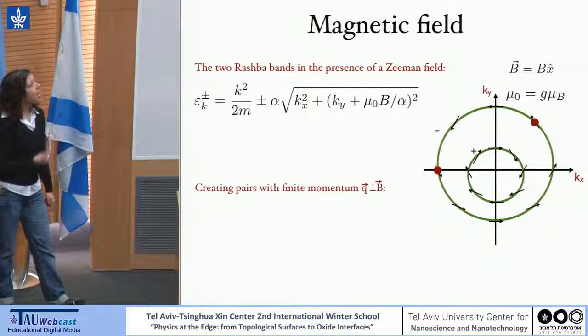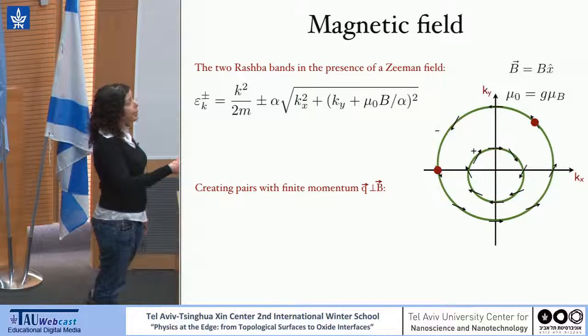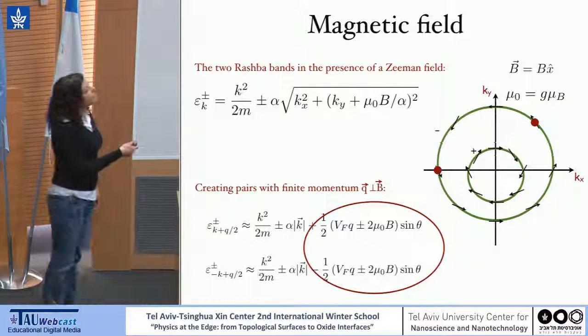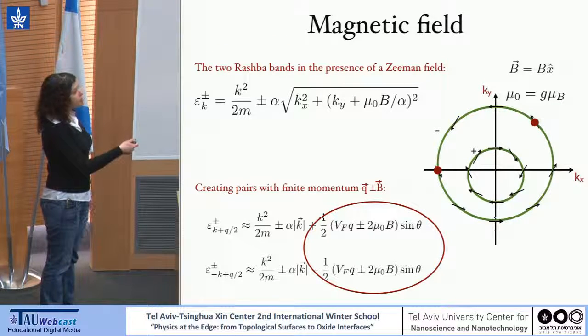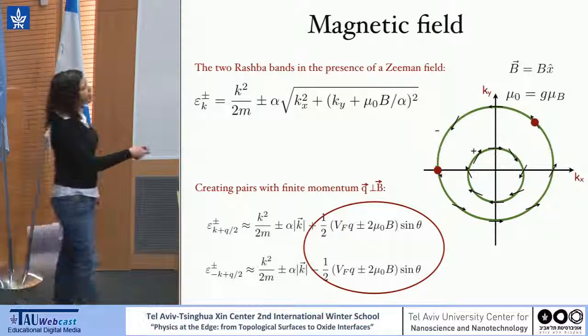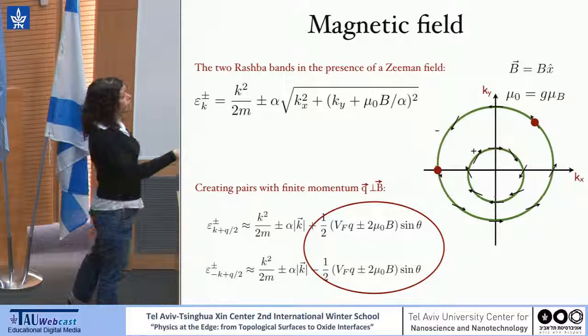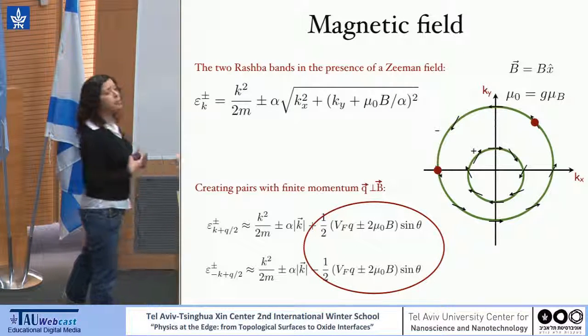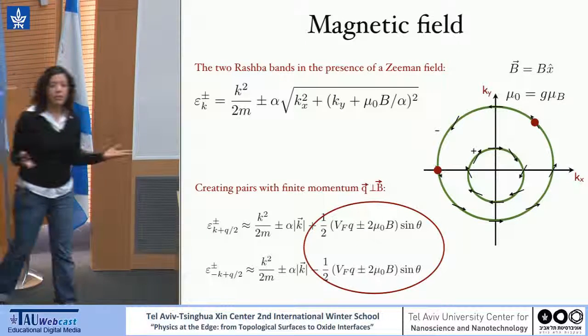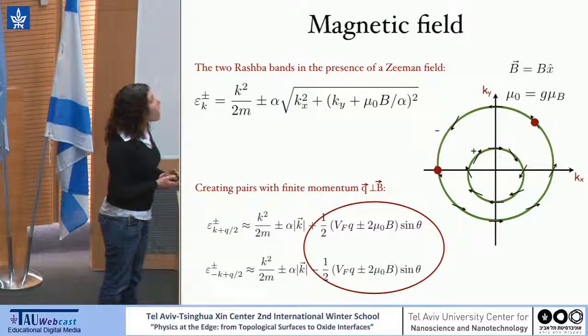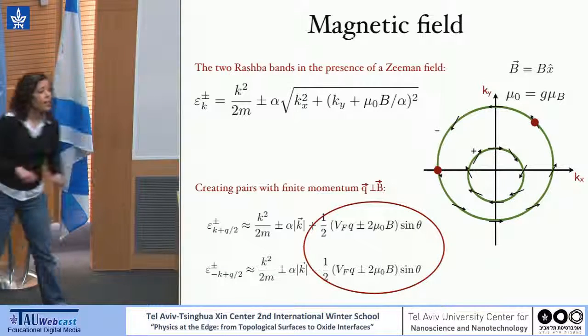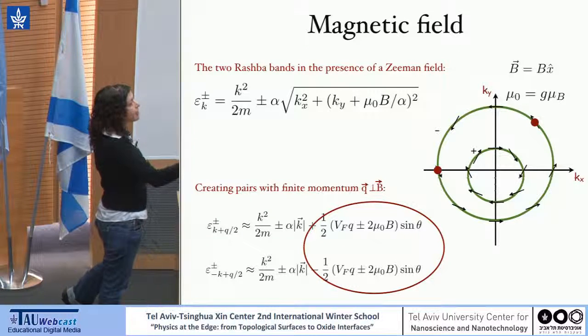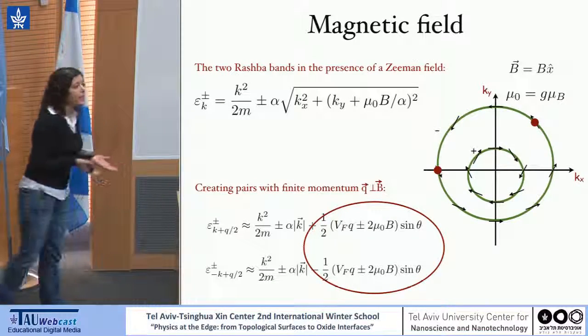However, if we try to pair electrons with finite pair momentum, we can see that the electronic spectrum for an electron with momentum k plus q over 2 and minus k plus q over 2 only differ by this value. If we can set this value to be 0 by tuning q, there is no effect of the magnetic field on the system. It depends on the angle around the Fermi surface. But since it just multiplies everything, if we set the value of q in such a way that q eliminates the second term, there is no effect of the magnetic field in the system.